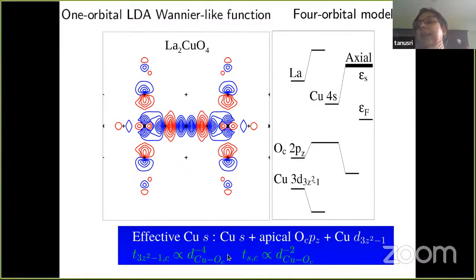This arises because of the hybridization between copper 4s, which is actually empty, and the apical oxygen, because all these structures have an oxygen atom sitting out of plane, as I will show a few slides later, and coupling with the copper 3z squared. And that basically gives rise to an effective orbital that we call an axial orbital, formed as a result of hybridization between copper s, apical oxygen pz, and copper 3z squared, and maybe even some out-of-plane, like lanthanum, degrees of freedom.